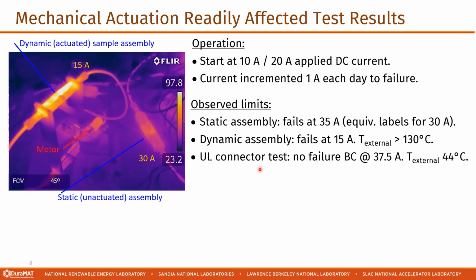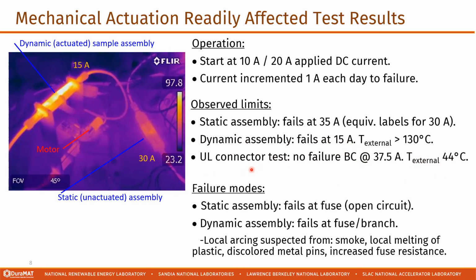If you compare that to the UL connector test, which I don't show an image of here, we're just looking at the branch connector on its own. We're running it at 37.5 amps, and it's reaching external temperatures of about 44°C. So that's comparable to the static assembly component, right? That's comparing current-wise. Speaking of the failure modes, the static assembly fails at the fuse. There's an internal conventional fuse component embedded in here, and it fails in open circuits. The dynamic assembly fails at the fuse branch interface. What's going on here includes smoke coming from the components, localized melting of the plastic, the metal pins are discolored when you pull them apart, and there's a slightly increased fuse resistance.